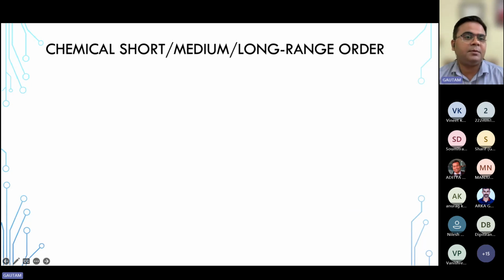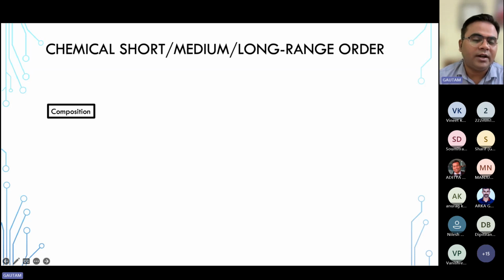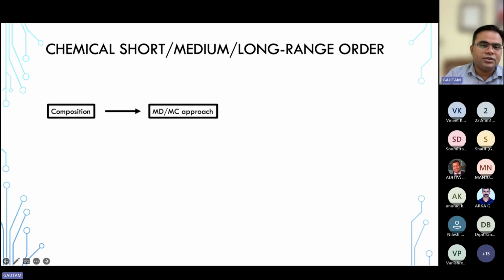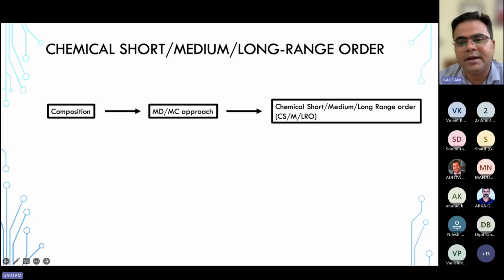There it is difficult because you have a number of components. Traditionally, chemical short range, medium range or long range order are studied in high entropy alloys for a given composition. You then use a combined molecular dynamics Monte Carlo approach, and using the Warren-Cowley parameter, you predict the chemical short, medium, or long range order of the system. But that involves knowing the energy of the system, and to know the energy, you need the interatomic potential file. But this is not an inverse approach. This is a forward approach.